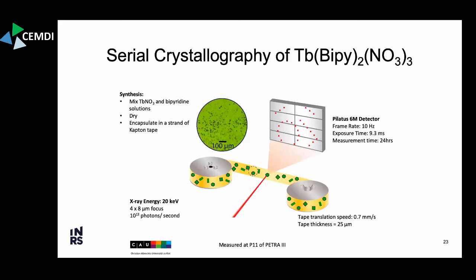And I will be showing you some examples of this state of the art based on some work that I did doing serial crystallography while in the group of Henry Chapman in Hamburg, Germany. Serial crystallography is where you use a small, tightly focused beam, could be electrons, could be X-rays. So your probe beam is small, and then you translate your sample in front of this small beam, and you rapidly collect diffraction patterns, reading out your detector as fast as you possibly can.